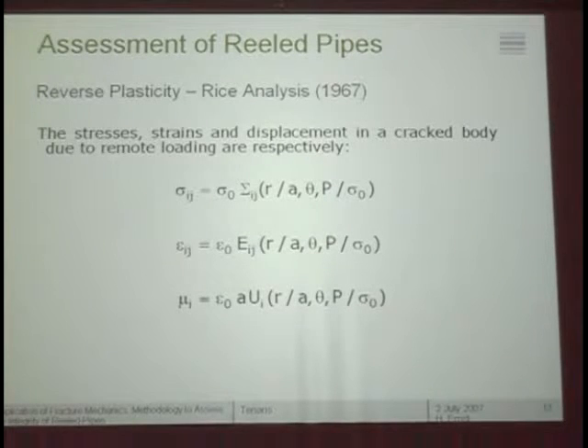In order to do that, we went back to the literature, and of course, who else? We found some very old paper by Rice, 1967, where he basically proposed that you can do something with the unloading for specific material constitutive equation, the kinematic hardening approach. If you have around the crack tip stresses, strains, and displacement given by some functional dependence like this, sigma 0 and some function of R, distance over A, angle, load, and yield, and so on for the rest,